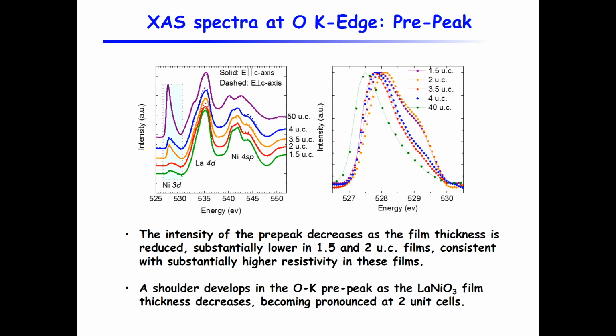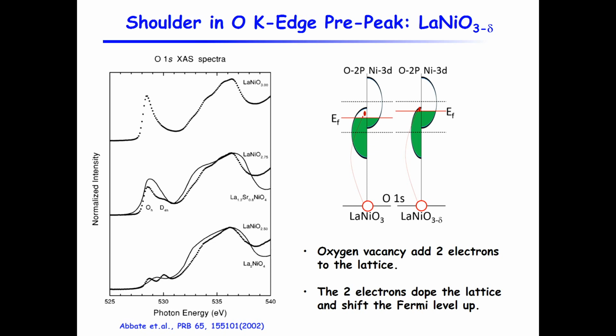And so one thing that they did not do in their calculation is they didn't really calculate the oxygen vacancies. In our X-ray absorption measurement, oxygen K edge, we measured this pre-peak, which is related to the hybridization of these P and D orbitals. And what we have found by looking at these peaks is that there is a feature that develops when we reduce the film thickness. A 40 unit cell film doesn't have a very pronounced feature here, but when we make it thinner, in particular at 2 and 1.5 unit cell, that feature develops. And that feature has been attributed to the oxygen deficiency. That's this feature here. Right?